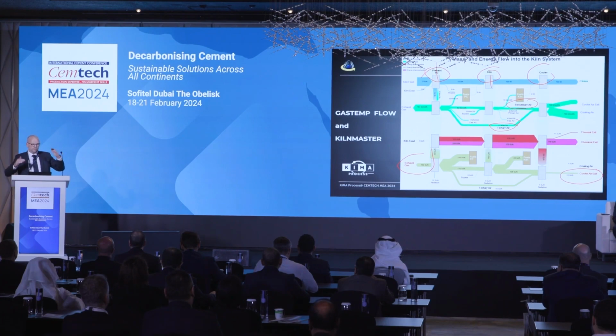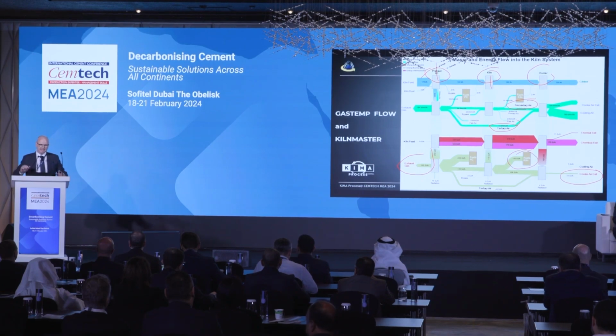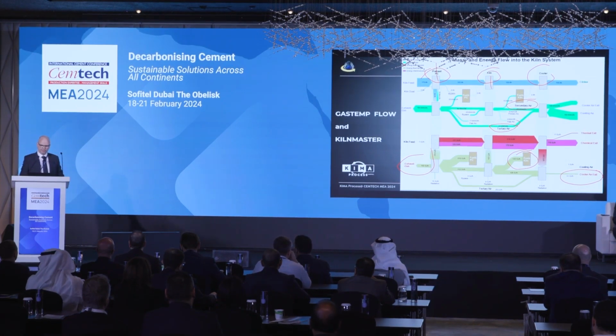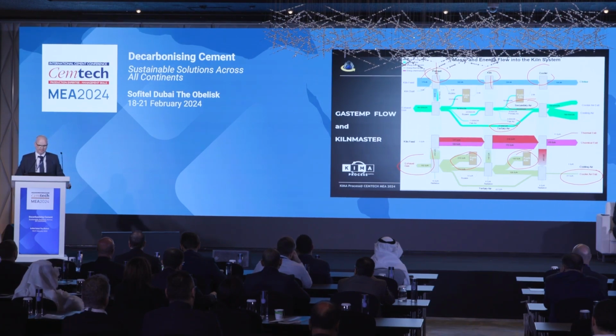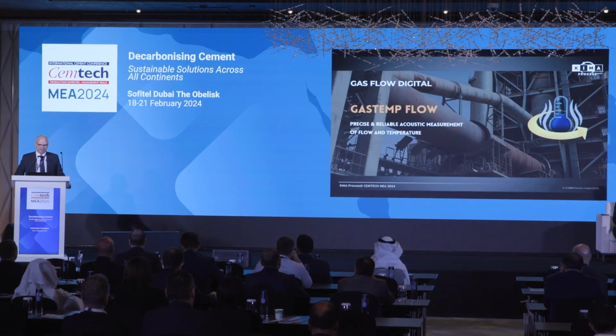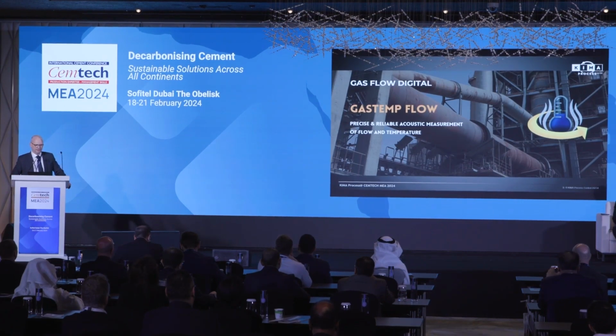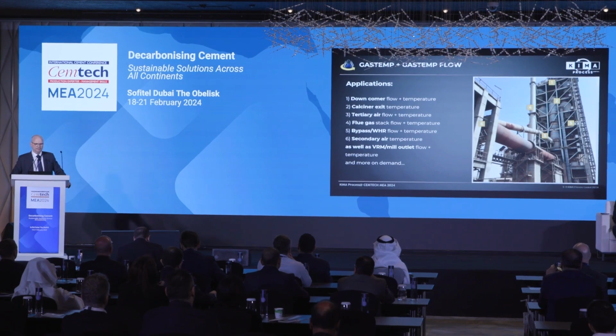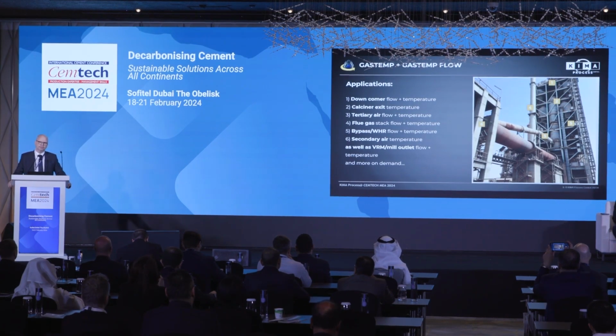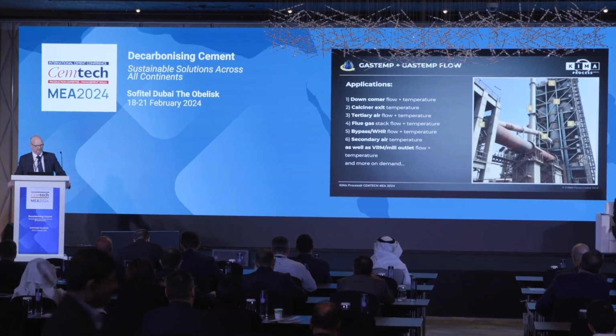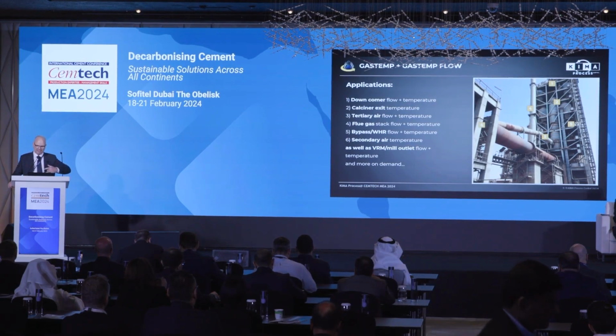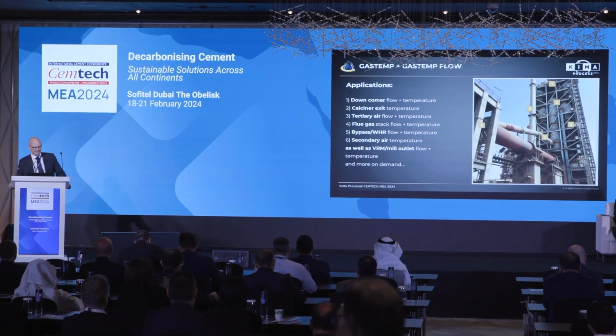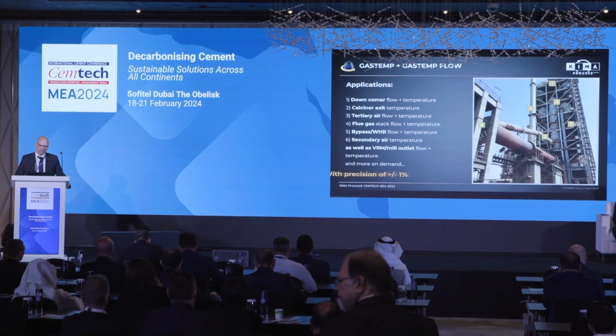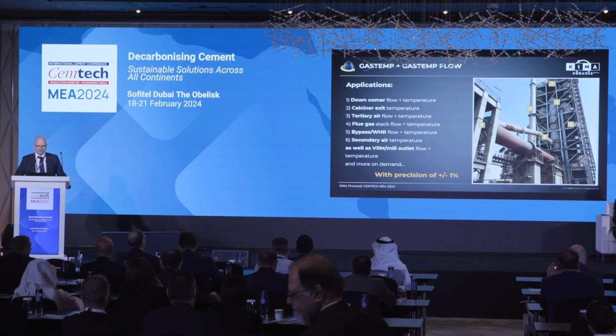With this reduction of the coefficients of variance and this precise control, we see if the kiln gets less fuel and energy from the main burner or from the preheater burner. Now, to measure this, and this is again the content today, we designed GasTemp and GasTemp Flow, an acoustic measurement which measures gas flows and temperature in very high dust-containing gases, also with changing dust content and with high temperatures up to 1,500 degrees. I would like to confront you with this measurement principle a little bit.